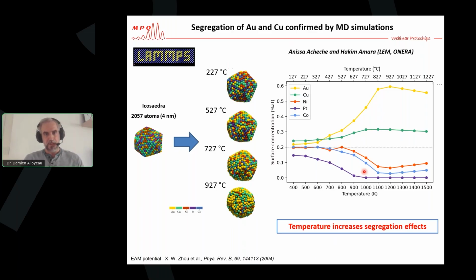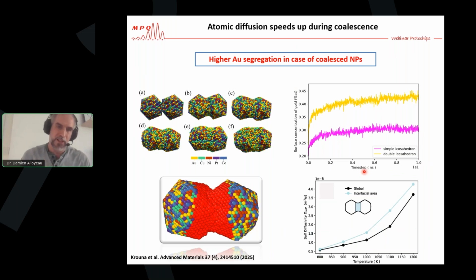Now, my colleagues have also been able to demonstrate that by running simulations on two very close high entropy nanoalloys. They simulated the coalescence of two clusters, and they realized that there is a much higher segregation effect of gold in the coalesced nanoparticles with respect to the single nanoparticles. And this effect is exactly the result that we also observed experimentally. They have been able to prove that this is due to the fact that when the particles coalesce, because of the restructuring of the nanostructure during coalescence, you have a much higher diffusivity of the gold inside the nanostructure. And as the diffusion of gold goes faster, you reach faster the thermodynamic equilibrium where gold atoms want to be at the surface.